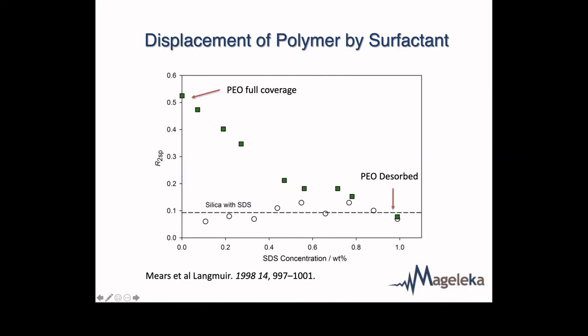So this is the bare silica value. This is the value with PEO, and just titrating in SDS makes it desorb. Now, one interesting thing you can do with this is that you can work out the strength of the polymer surface interaction from the concentration of surfactant needed to desorb it. So it's like doing a calorimetry experiment, but getting an actual number from the absorption energy.